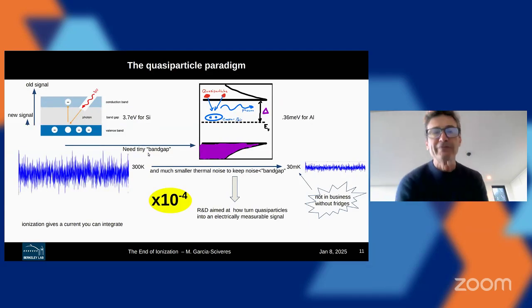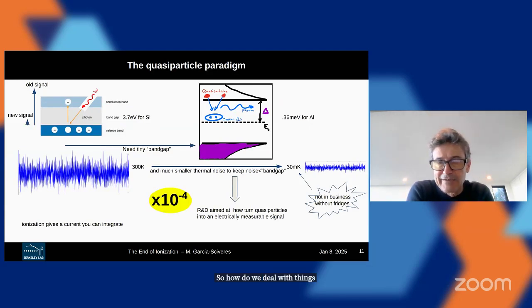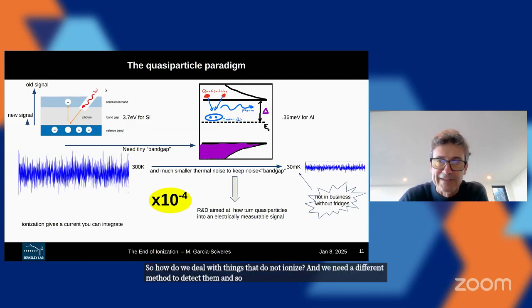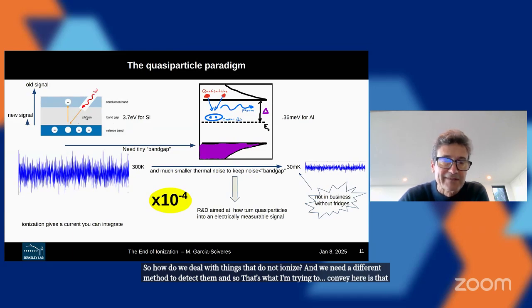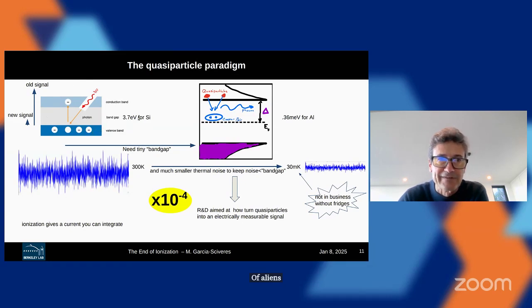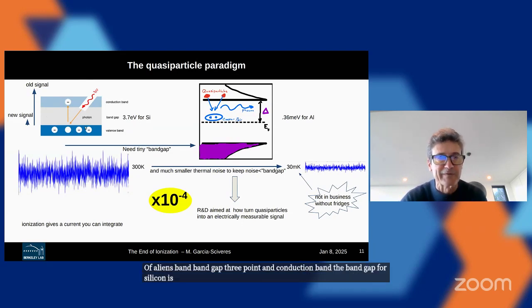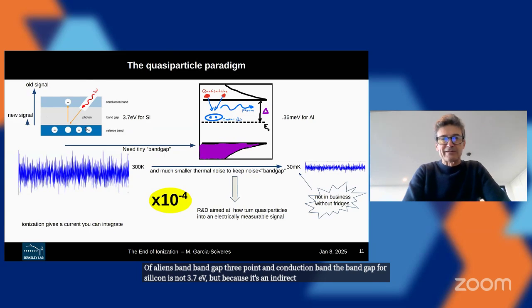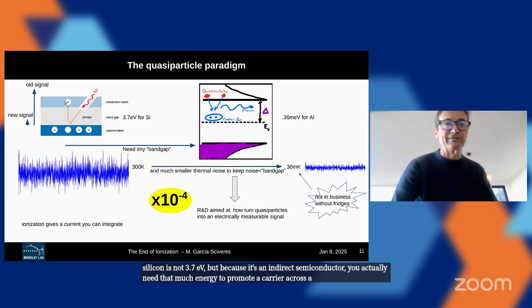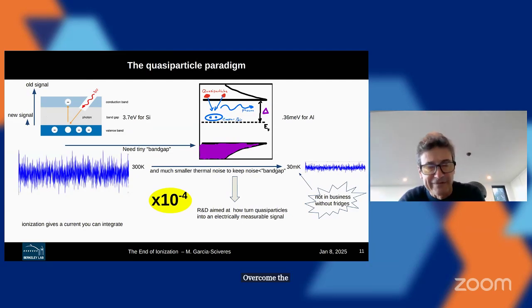So how do we deal with things that do not ionize? We need a different method to detect them. And so that's what I'm trying to convey here. Let's start with a semiconductor, because there's a very good analogy here. In a semiconductor detector, you have a valence band, band gap, and conduction band. The band gap for silicon is not 3.7 eV, but because it's an indirect semiconductor, you actually need that much energy to promote a carrier across the band gap, because not only do you have to overcome the energy of the band gap, you also have to match momentum.